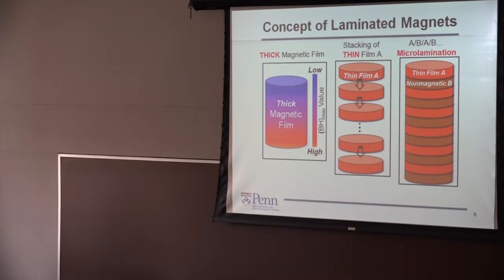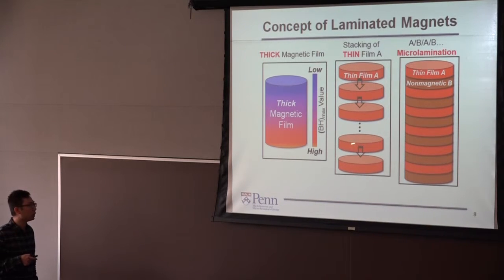So given all these constraints, is there a way to have both large thickness and high energy density at the same time? We see that as thickness grows, the property decreases. One thought is that since you suffer from this property degradation when you get a thick film, why don't you have thin films and stack them all together? So you can get both good property from the thin film and a very large thickness. There are several ways to technically realize this. One way is self-assembly, where you bring the films together with some favorable forces, let's say capillary forces.